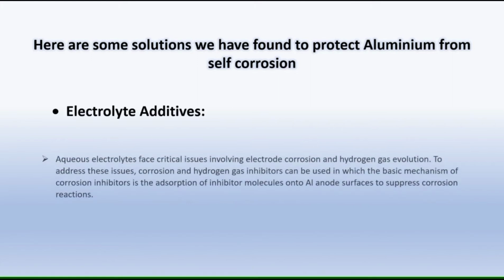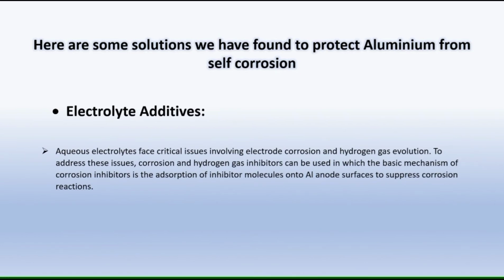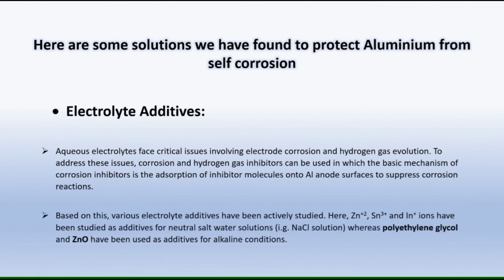Electrolyte additives. Aqueous electrolytes face critical issues involving electrode corrosion and hydrogen gas evolution. To address these issues, corrosion and hydrogen gas inhibitors can be used, in which the basic mechanism of corrosion inhibitors is the adsorption of inhibitor molecules onto the aluminum anode surface to suppress corrosion reactions. Based on this, various electrolyte additives have been actively studied. Here, Zn2+, Sn3+ and In+ ions have been studied as additives for neutral salt water solutions such as NaCl solution, whereas polyethylene glycol and ZnO have been used as additives for alkaline conditions.